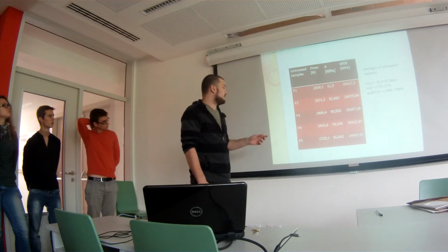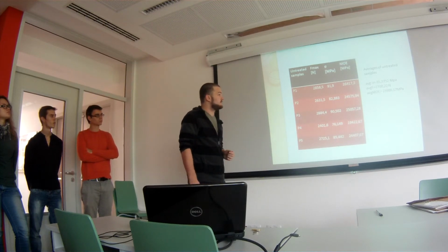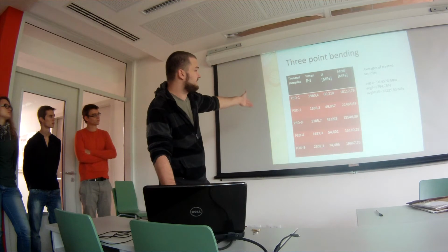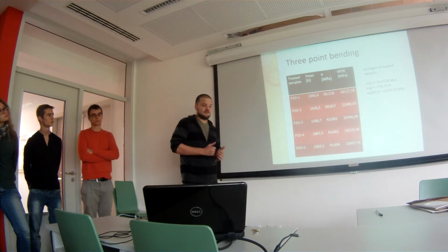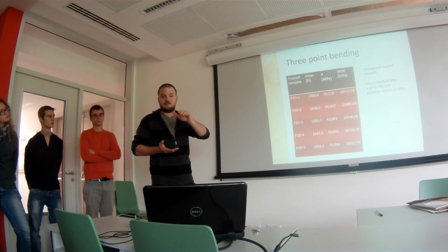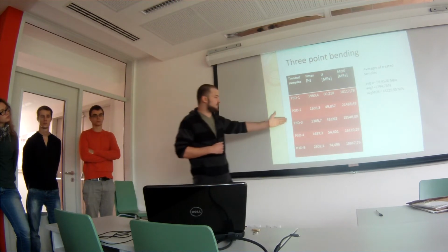First one, the untreated sample, you can see the force is pretty high. Most of the time it's over 2,500 newtons, and in the treated samples it decreases drastically. And it's not only these five, because we have more samples. We chose to use the best ones, and these are the best ones.